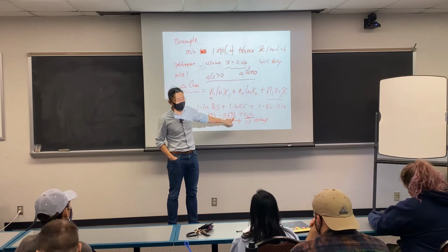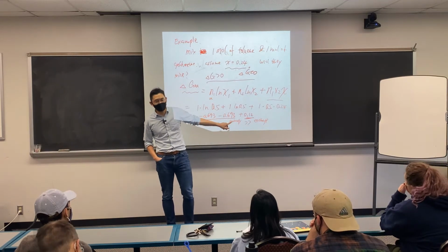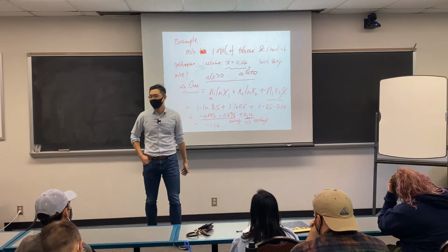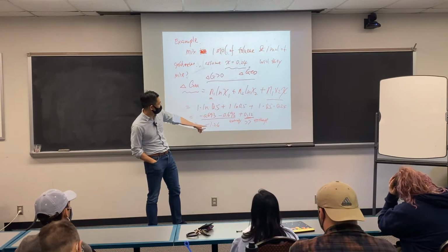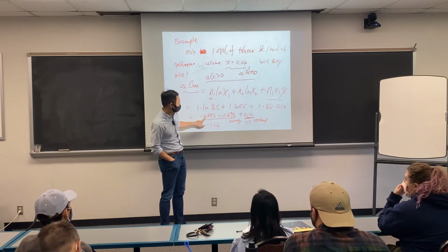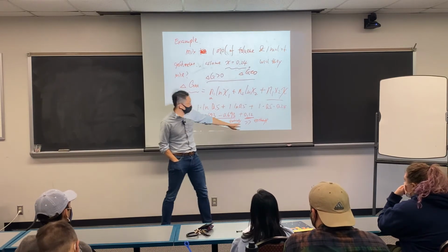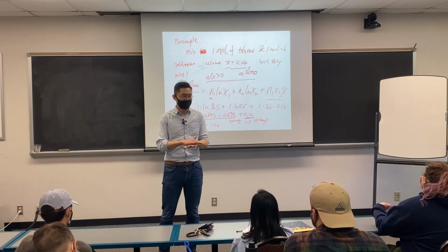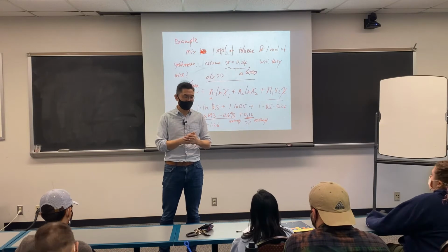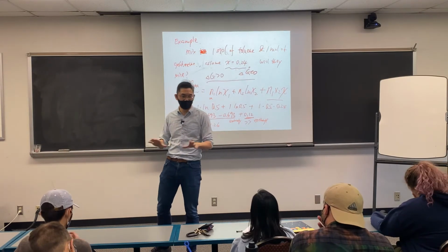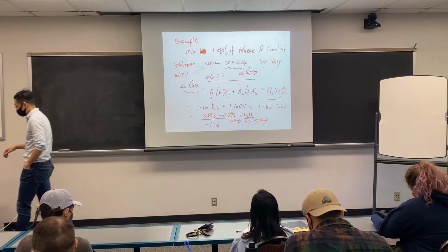But however, let's go to another thought. When we mix two polymers, both with dP about 100, then this will be 0.07 roughly. This will be 0.07. Then the entropy is finally going to lose the game. It says, oh, there's not much entropy gain when you mix two polymers, so they're not going to mix. In this case, it will phase separate. Okay?